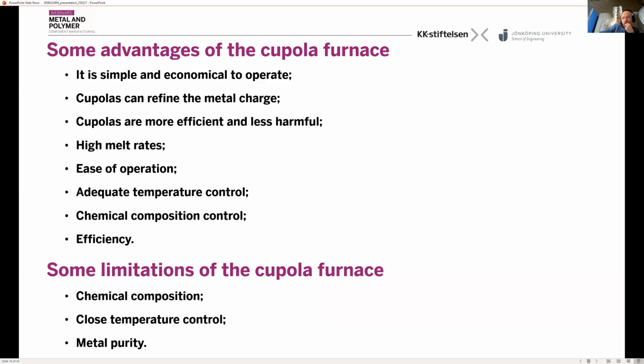Some of the advantages of the cupola furnace: it's simple and economical to operate. So it has quite a low cost of melting. Cupolas can refine the metal charge by removing the impurities out of the slag. Cupola furnaces are more efficient and less harmful. High melt rates, easy to operate. The temperature control is adequate. Finally, the chemical composition may be controlled. And not the last is the efficiency of cupola that may vary from 30 to 50%.